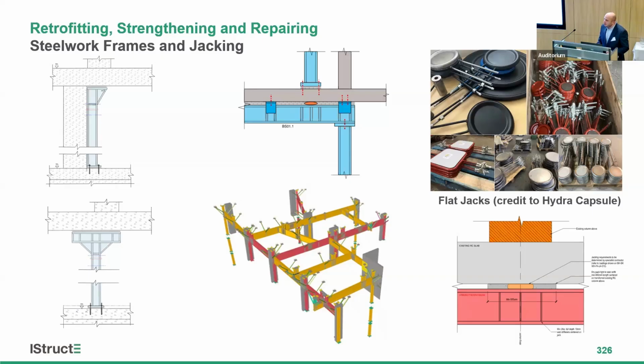Because punching shear is a brittle failure and the slabs do not deform very much before they fail, it is recommended that the steelwork is stiff enough to actively be engaged to prevent the slab from failing before the steelwork provides support. So either you should make the steelwork very stiff, or you should combine it with jacking, or do a combination of both of those.